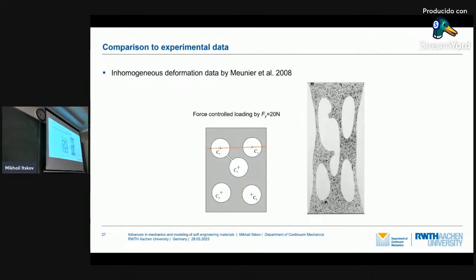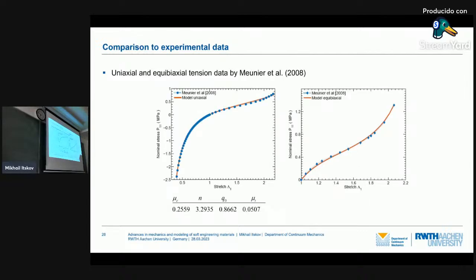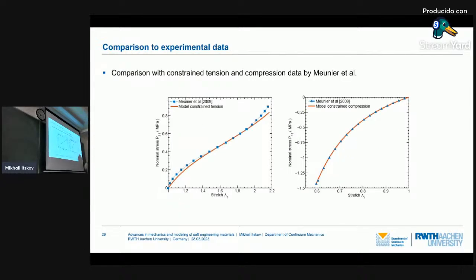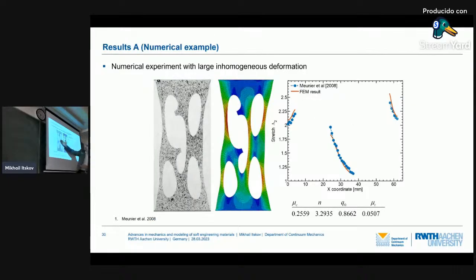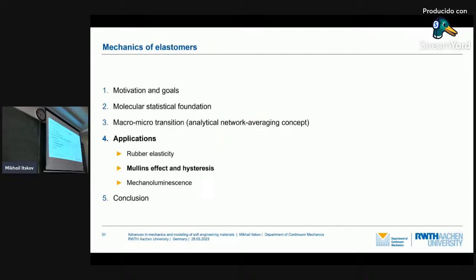Another example is an inhomogeneous example, such a plate with 5 holes subjected to tension, and along this line these displacements were measured, and we fitted our model to this experimental data, for example, the stress-strain curve in uniaxial tension and biaxial tension. Also, you see here constrained tension, constrained compression, and finally, you see the agreement is also for this inhomogeneity very good. Also, the displacements are very well described along this line.